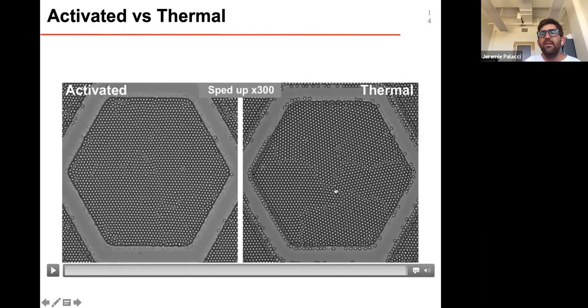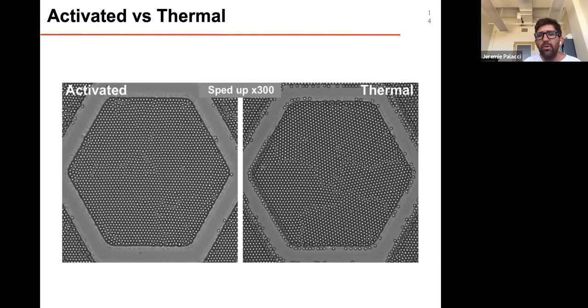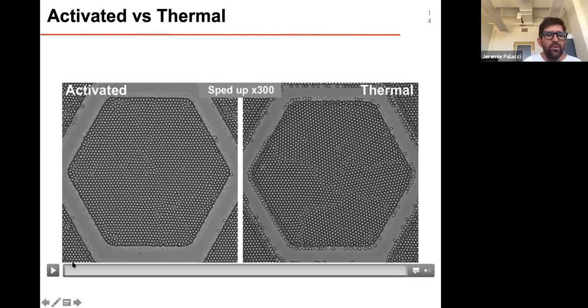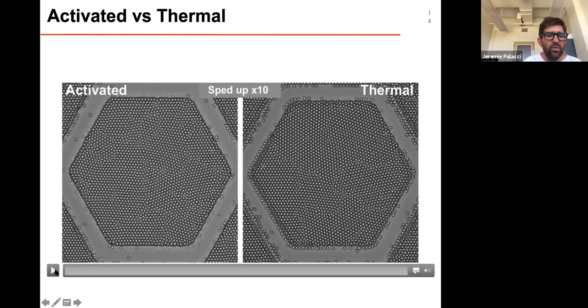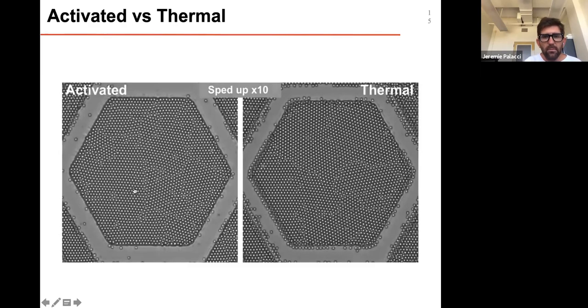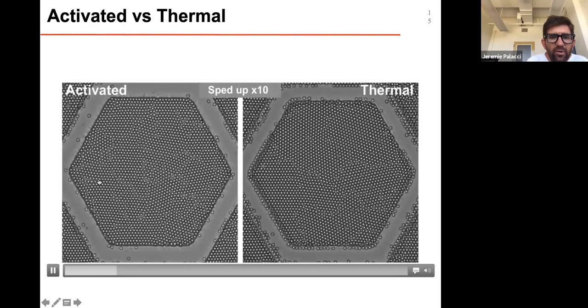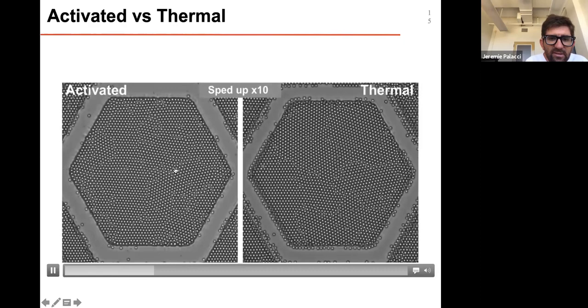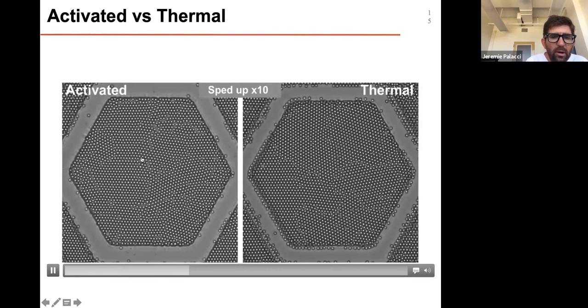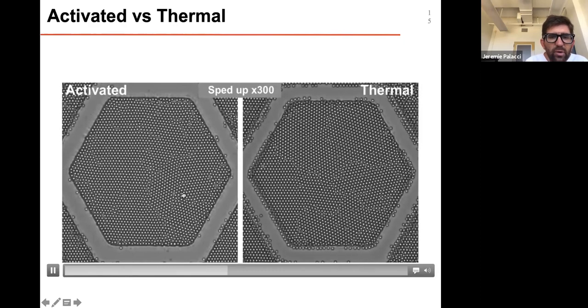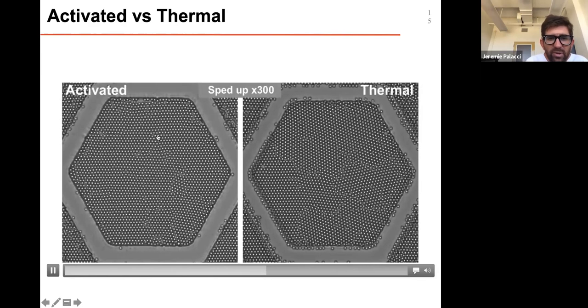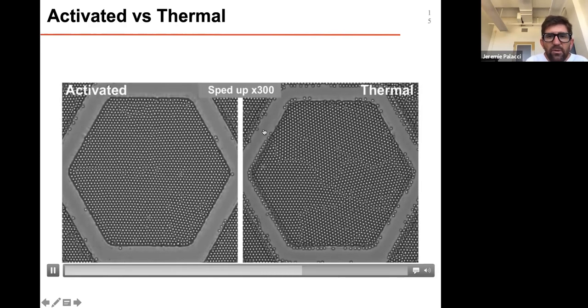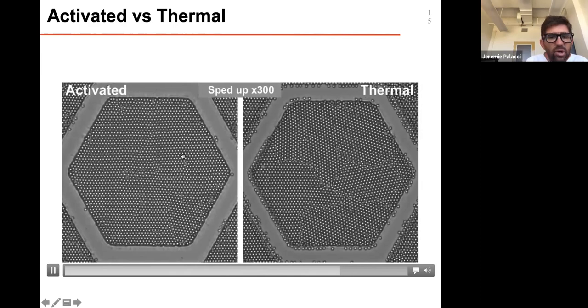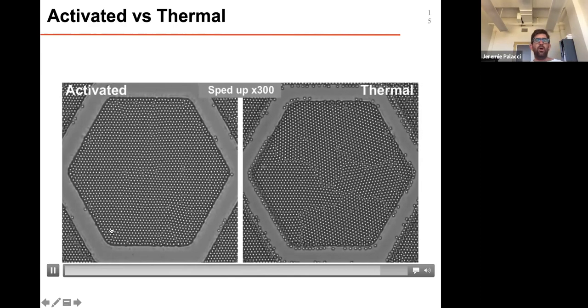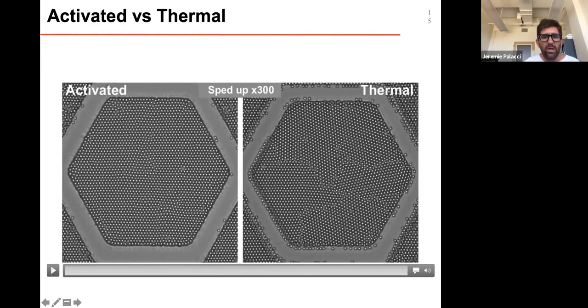Now that we agree that not much happens on the thermal side, let's look at what happens on the activated side. So I restart the movie. Now you see that it's very different. It's much more dynamic, and actually we can see streaks. Those streaks in the crystal are a result of the propulsion of the active particles. You see it's only a few of them. Once we speed up 300 times, we see that after about 30 minutes, we converted our whole polycrystal into one large crystal.